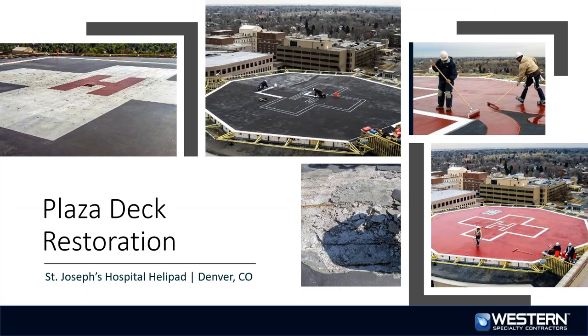This is another type of plaza deck restoration that we actually did here in Denver a few years ago. This is a helipad on one of the local hospitals. Probably the biggest challenge to this particular project is by the time it got started, it was in the dead of winter. The coating was put on when the temperatures were in the 10 to 20 degree range. We ended up using a methyl methacrylate on this because that allowed us to do it at the colder temperatures, but you still have a lot of restrictions and a lot of issues associated with that.